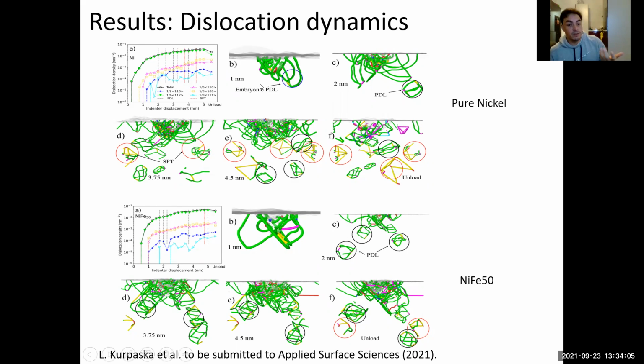I'm going to show a movie about this, but I want to discuss first what is the correspondence between the dislocation density as a function of the indenter displacement for nickel. For nickel, even you can see that in the elastic part, you only see the Shockley partials. But then when you are going to the plastic deformation transition, you can start nucleating other types of dislocations. So then you are going to find the Hirth and the Frank junctions. Here is the junction, and I'm going to show how the junctions are.